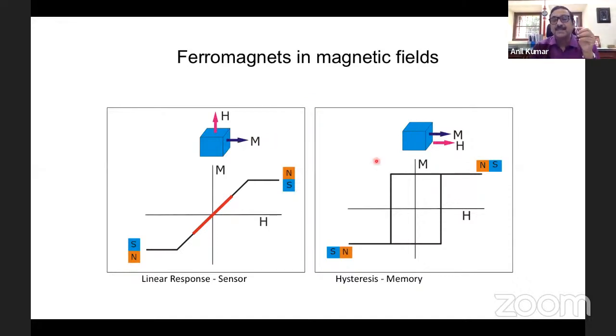Now, if I apply the magnetic field along the easy axis of magnetization, and if I measure the magnetic moment, you see that if I apply sufficiently high magnetic field, the magnetization is here. Now, even if I remove this magnetic field, reduce it back to zero, still it will have 100% remanence. So it is fully magnetized. And if I reverse this magnetic field and go to the negative direction, above a critical field, the magnetization reverses from plus M to minus M. And this is called the magnetization reversal. And this field is known as the critical field or the coercive field of this material. Now, if you increase further, you get this saturation here, and when you come back again, full magnetization, and again you reverse it, and you get this hysteresis loop.